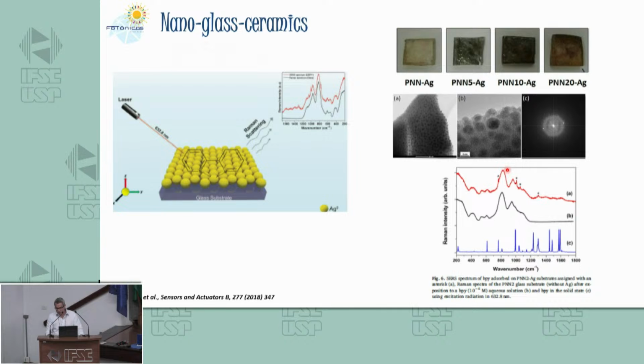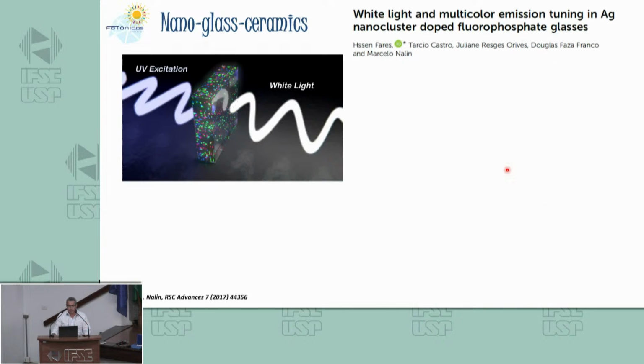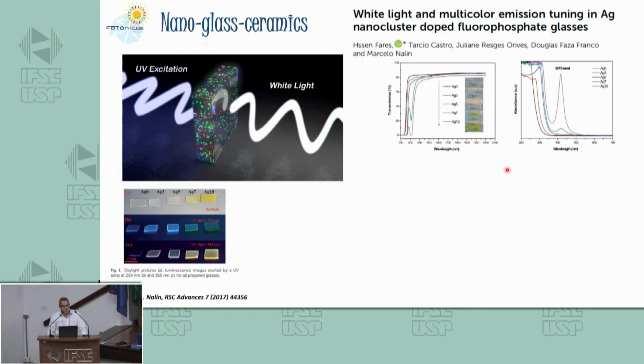Okay, so it's in a solution of 10 to the minus 6 mol per liter. So it's quite nice. So we can also use nanometallic crystals inside glass to get white light emission. In this paper, we produce some glasses just controlling the amount of silver inside the glass.